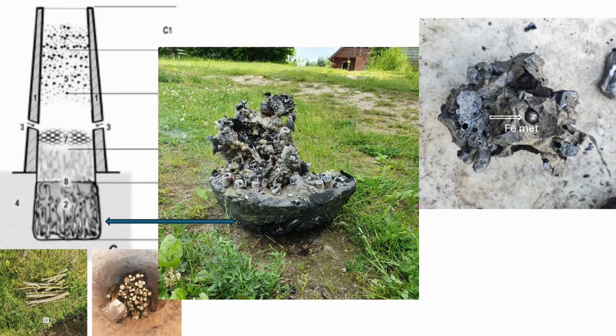more elemental iron in the divalent form, indicating more reducing conditions. The structure resembled archaeological slags and showed properties of fayalite. However, the iron remained phosphorus-rich, with some areas unevenly carburized, while others displayed characteristics of cast iron.